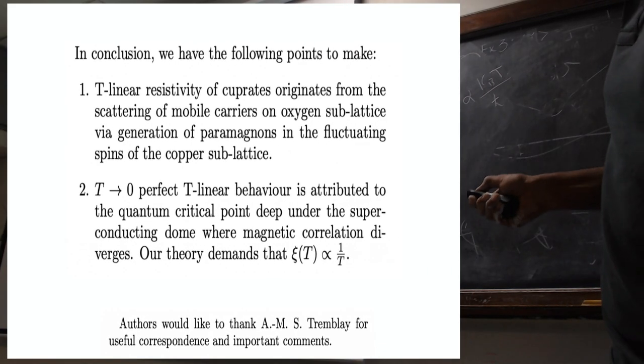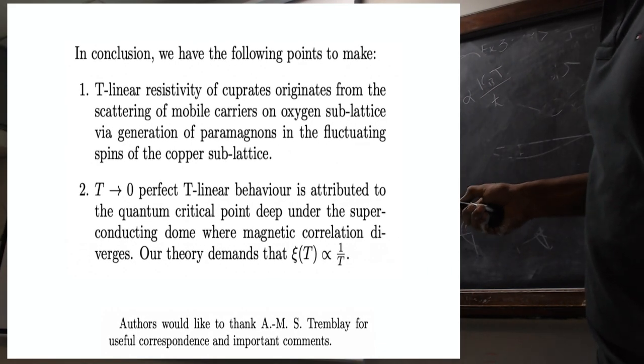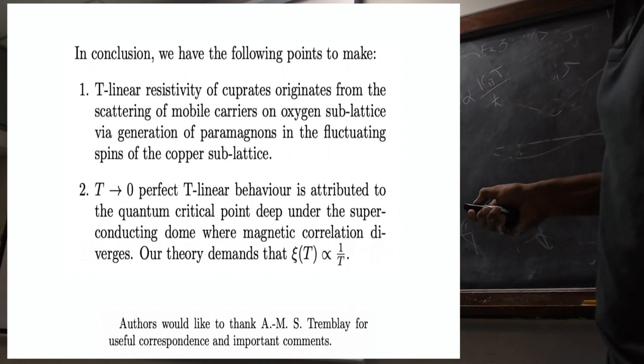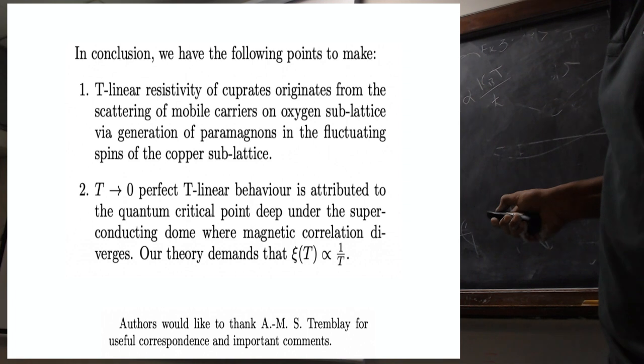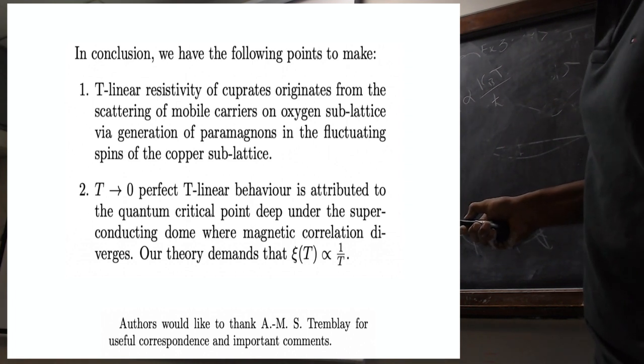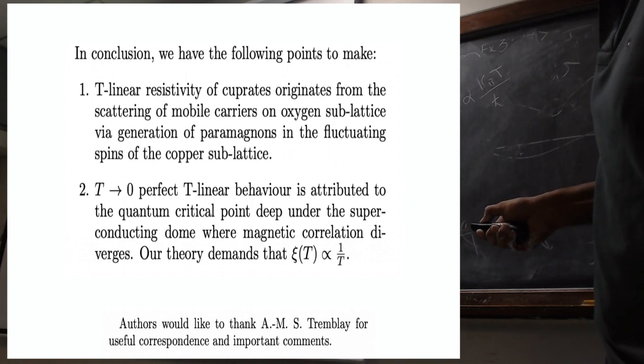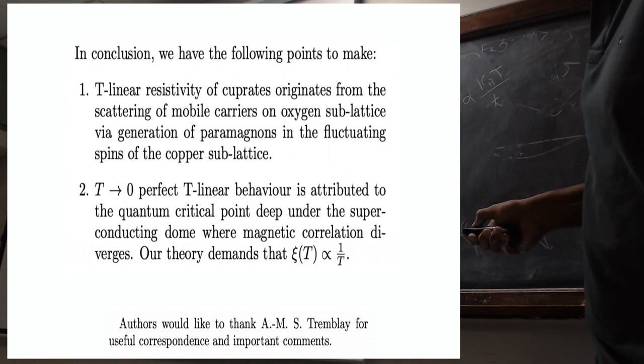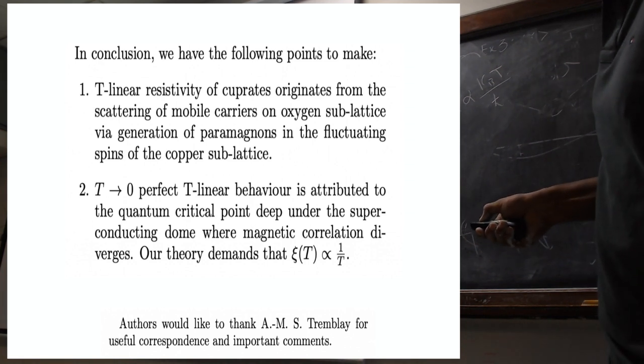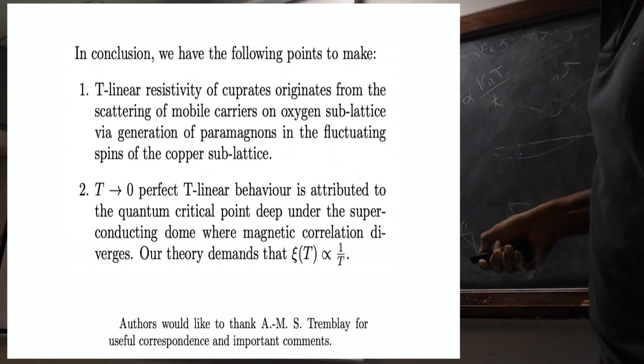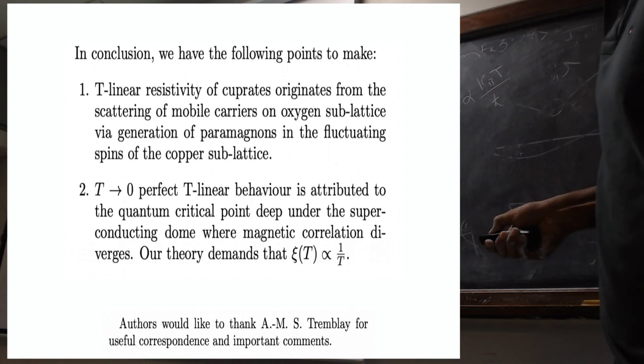Okay. In conclusion, the following points I want to make: linear resistivity in cuprates originates from scattering of mobile carriers on the oxygen sublattice by generation of paramagnons on the fluctuating spins on the copper sublattice. The T-linear behavior is perfectly attributed to a quantum critical point deep inside the superconducting dome, and the magnetic correlation length. Our theory demands this. Okay, so we have been sort of discussing this issue with Tremblay.